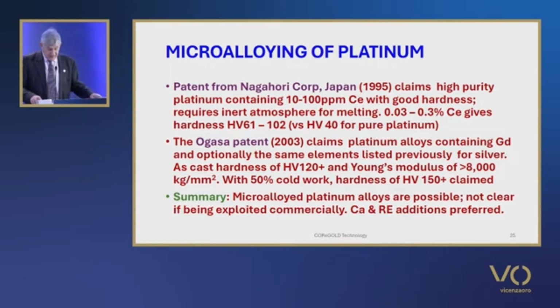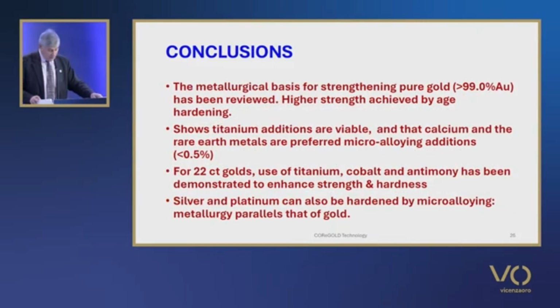Thus, in summary, it is evident that microalloyed platinum alloys are possible, although it is not clear whether they're being commercially produced, and that the rare earths and calcium are preferred microalloying additions, paralleling that of the work on gold. So we can just come to my last slide. I think we can conclude that the metallurgical basis for strengthening and hardening 24-karat gold of at least 990 fineness has been reviewed. This shows that as well as titanium additions, calcium and the rare earths are the preferred microalloying additions, but other possibilities have been noted.